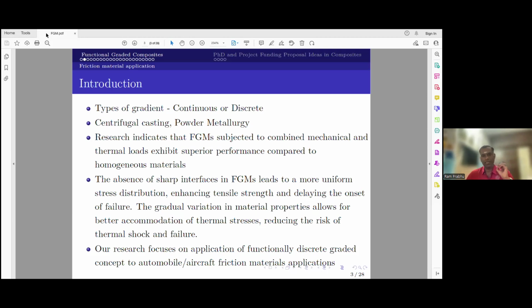The reason is you don't have sharp interfaces in FGM. That leads to a much more uniform stress distribution, which enhances not only your strength but also delays crack initiation and propagation, improving the toughness of the material. And in the thermal area, a systematically graded structure better accommodates thermal stresses, reducing thermal shock failures in the materials. So today I'm going to talk about functionally discrete graded composites for aircraft brake applications.